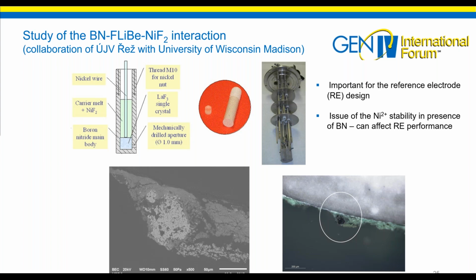This area is now studied by UJV Rez, and UJV now also collaborates with the University of Wisconsin-Madison to investigate the long-term stability of the electrode, because the stability is time-limited. In the drawings and pictures here, there is a schematic design of the reference electrode, the electrode set, and photos of the electrode surface. And here, inside the circle, you can see some small interaction of metallic nickel with the surface of the electrode body. So after some time, it can negatively affect the long-term stability, but for all that, this type of reference electrode seems to be probably the best one for the fluoride media.